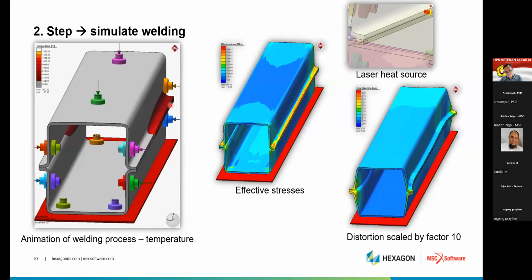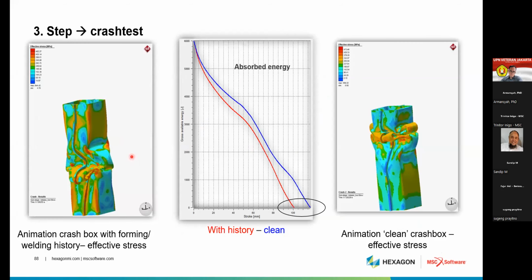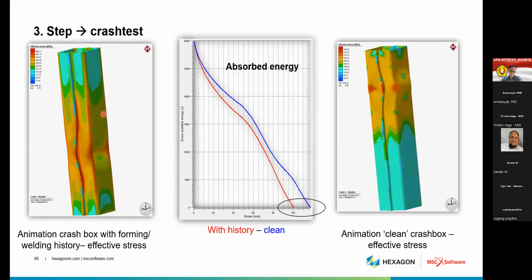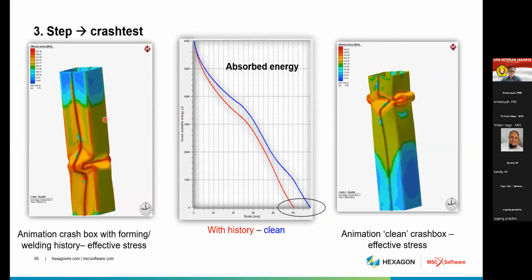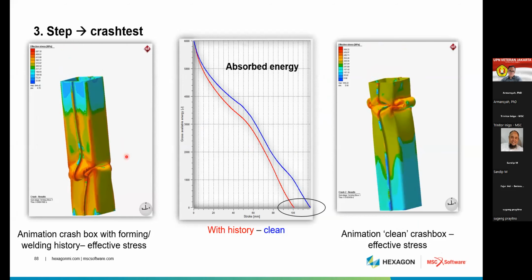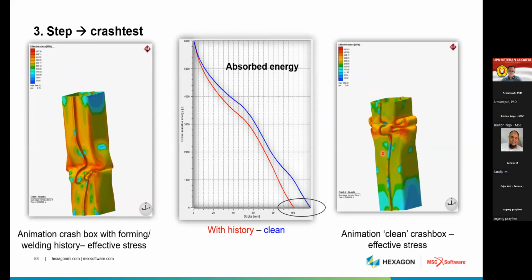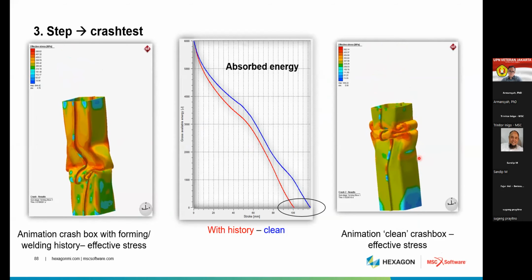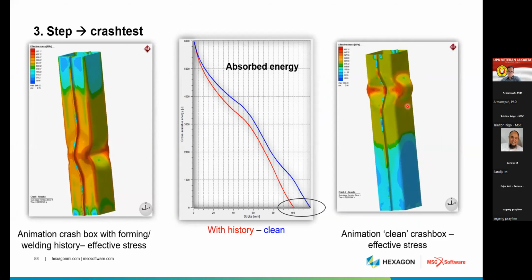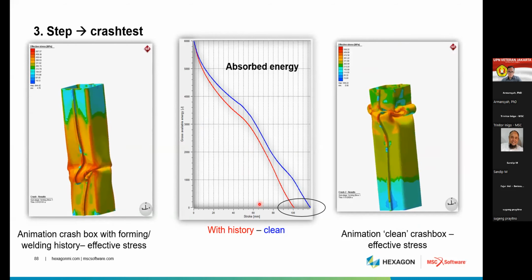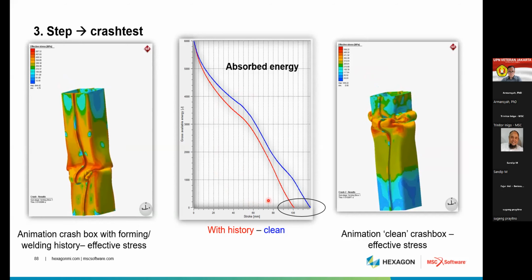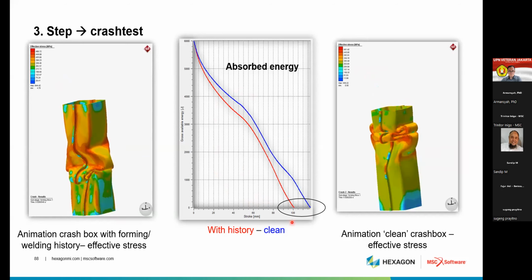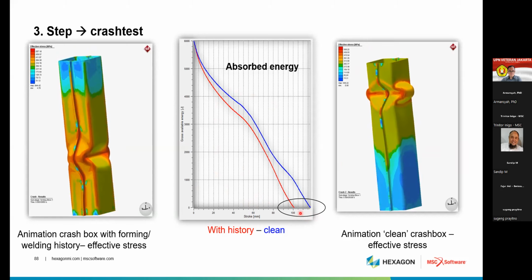And you can see this welding operation is happening. So this is my base plate. These are the fixtures. And as an output, we get the stresses and the distortion. And this is the crash test we did. In one case, we have considered all the forming and welding history. And in one case, we have not considered any history. So you can clearly see that the location of the distortion is totally different. And the graph showcases the absorbed energy by the crash box during that crash test. You can see there is a clear difference.